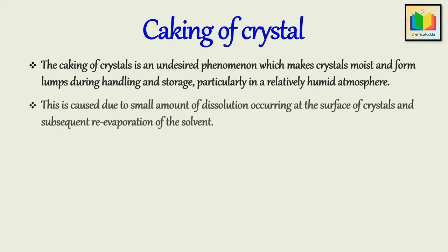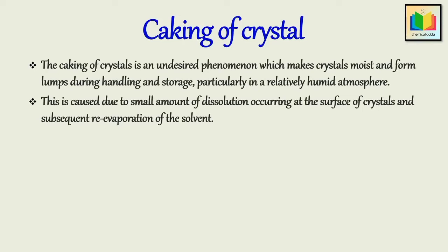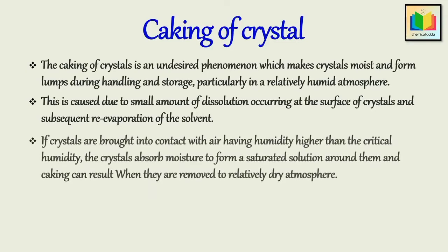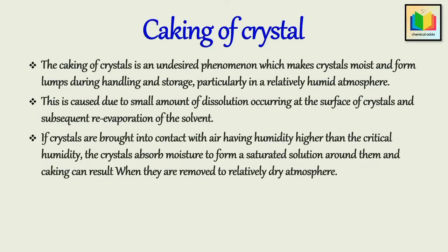This is caused due to a small amount of dissolution occurring at the surface of crystals and subsequent re-evaporation of the solvent. If crystals are brought into contact with air having humidity higher than the critical humidity, then the crystals absorb moisture to form a saturated solution around them, and hence the solution which is formed penetrates into the pack of crystals as a result of capillary action of the small gaps between the crystals. Caking can result when they are removed to a relatively dry atmosphere.